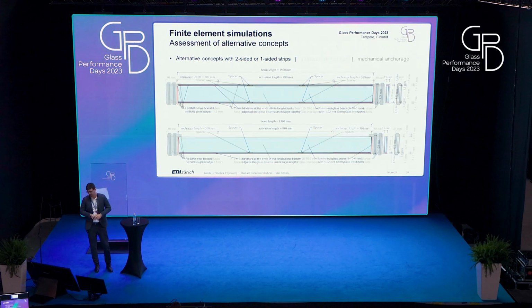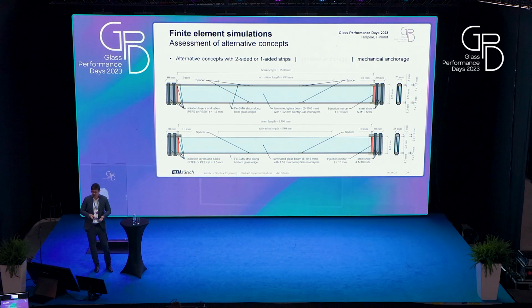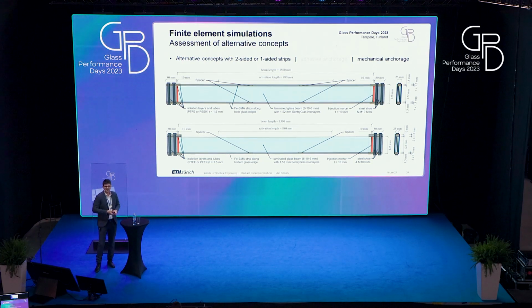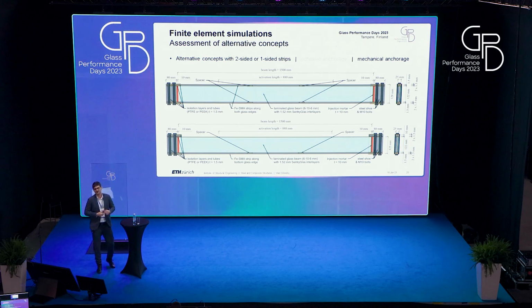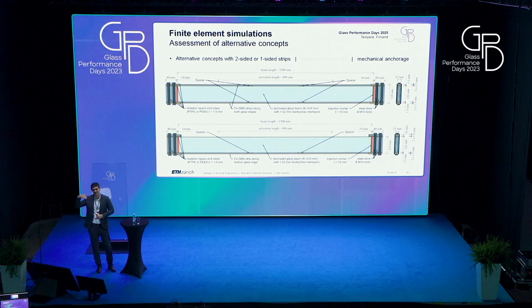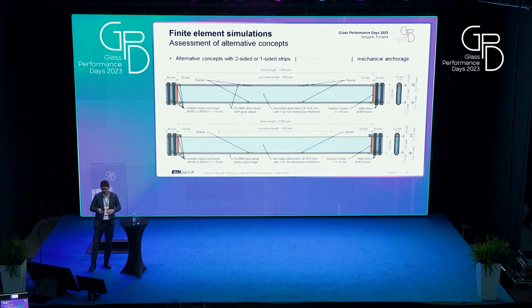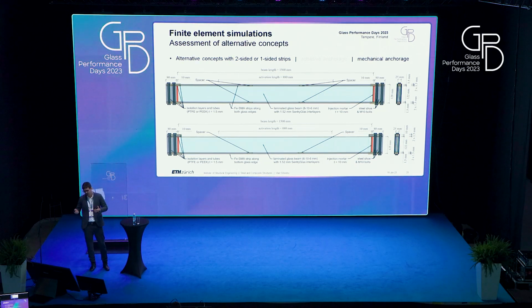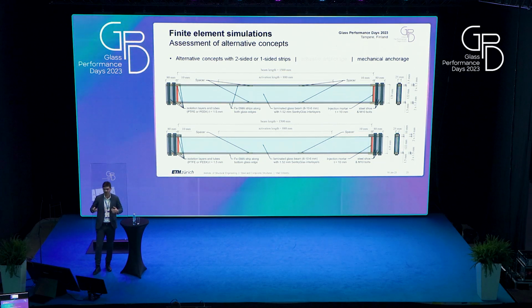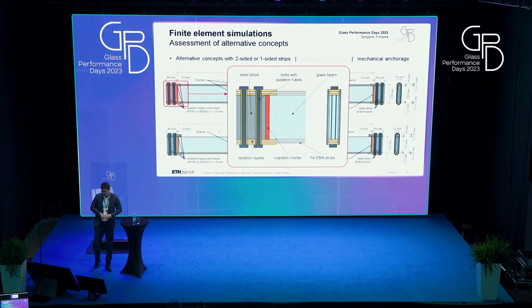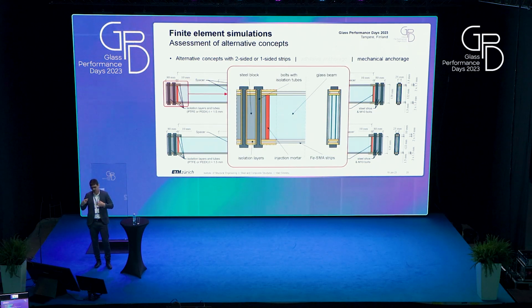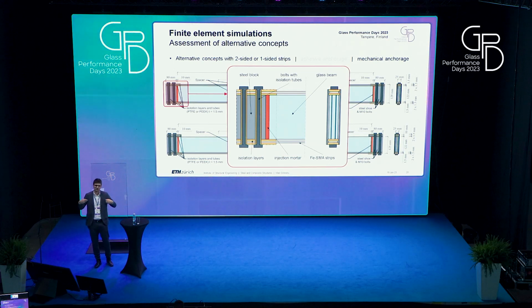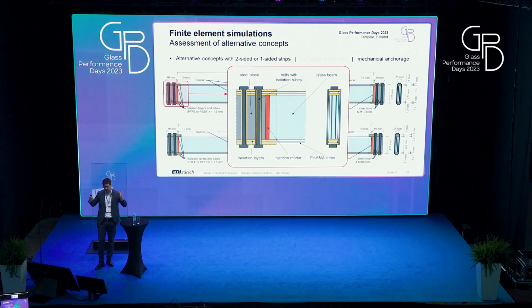And then also systems with mechanical anchorage, because I'm now attending conferences for glass for the last 10 years, and the trend for adhesive connections is somehow going downwards, at least that's my feeling, probably because of the whole reuse topic. So we thought, are we able to achieve similar results without using adhesive, only with mechanical anchorage? For this, the strips are fixed to steel blocks, which are positioned at the end of the glass beams, and the pre-stress is actually then introduced through some grouting at the ends of the beams.